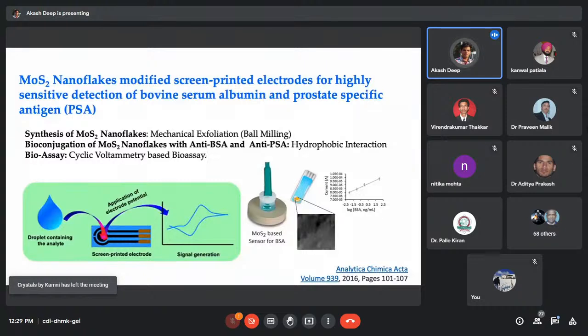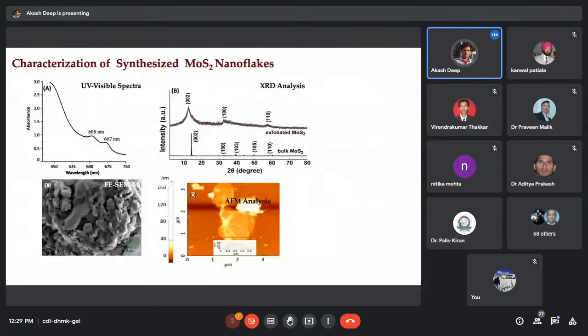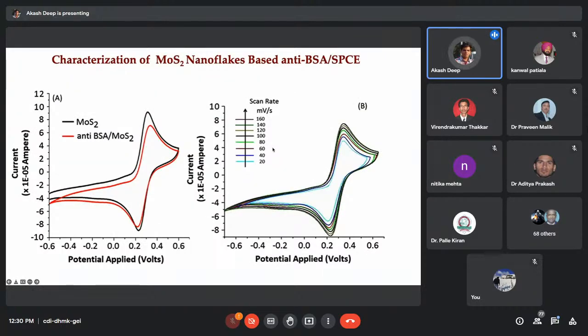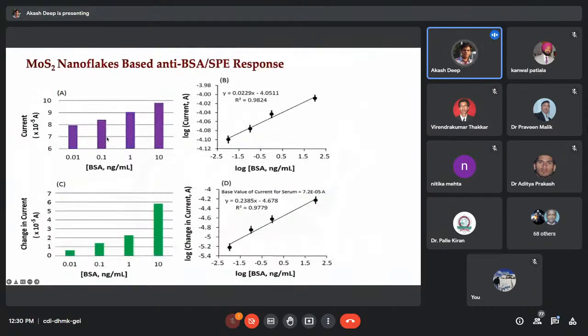These nanomaterials are synthesized with the help of different technologies, characterized using XRD or UV visible spectra. So here in this AFM analysis, you can see very fine sheets have been formed with a layer thickness of around 10 to 15 nanometer. Then we characterized them with cyclic voltammetry. I can show you the response here.